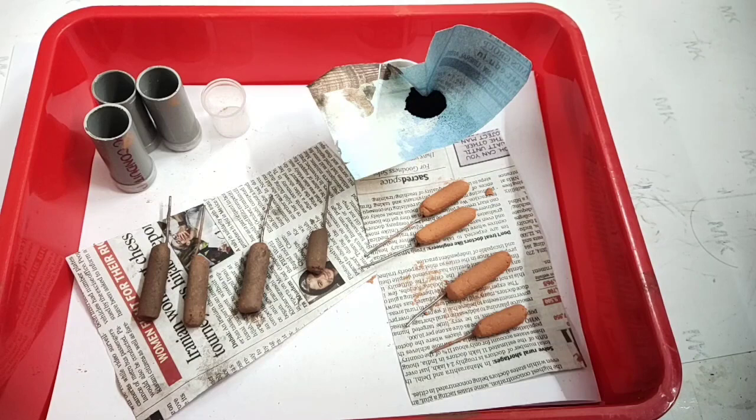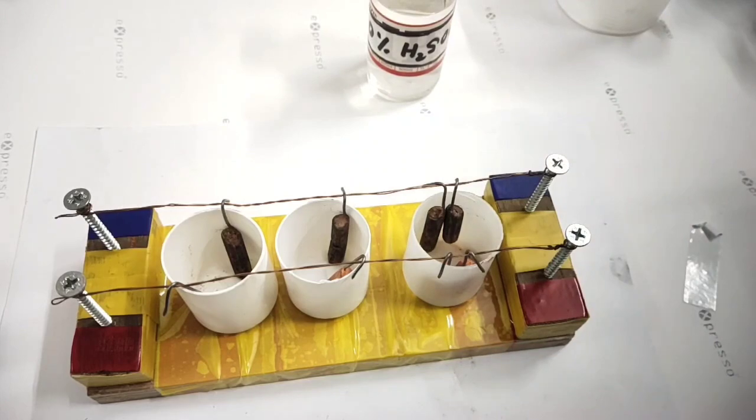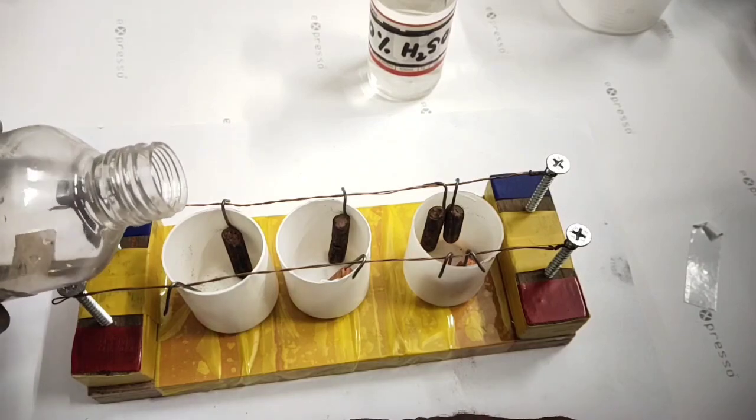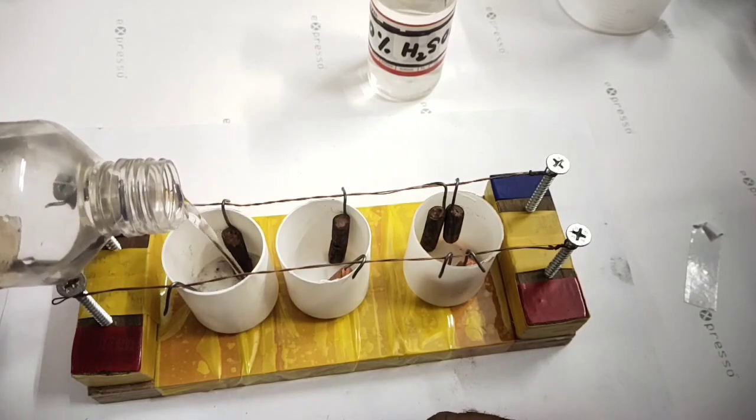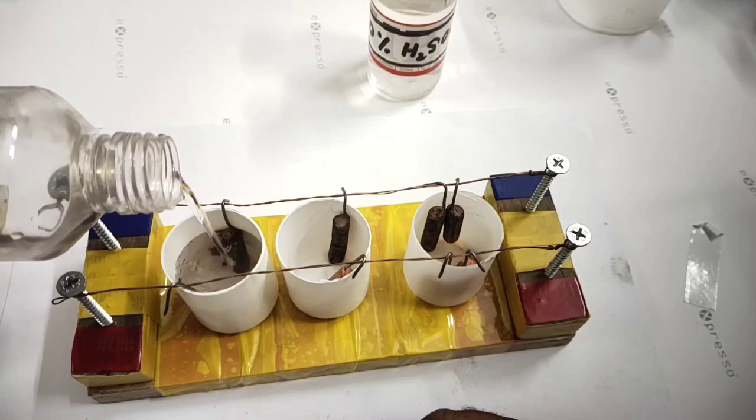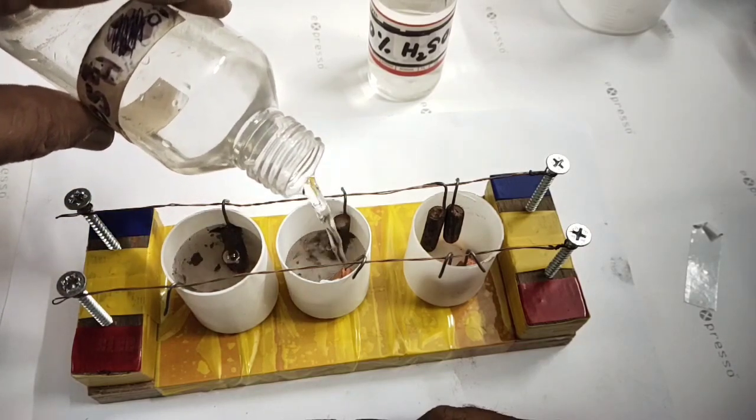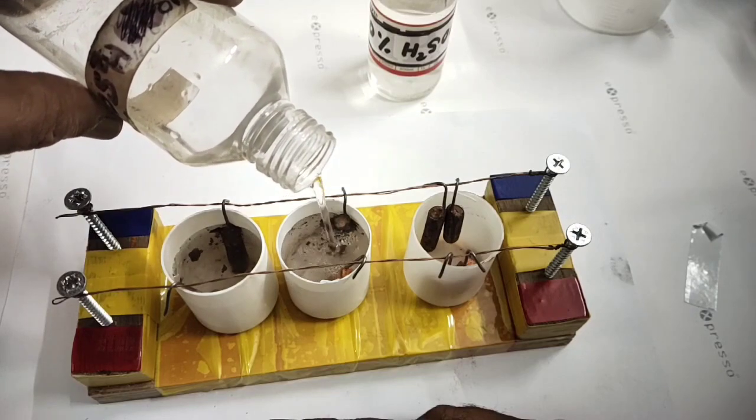They are to be kept dry for 48 hours, then soaking in 10 percent sulfuric acid for 45 minutes. That 10 percent sulfuric acid you can add so that the dried electrodes will become wet. We have to keep it for 45 minutes.